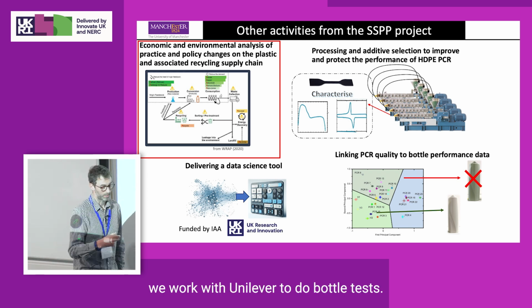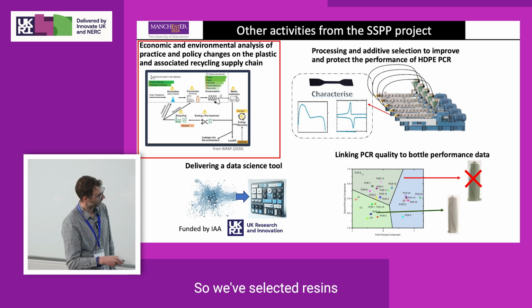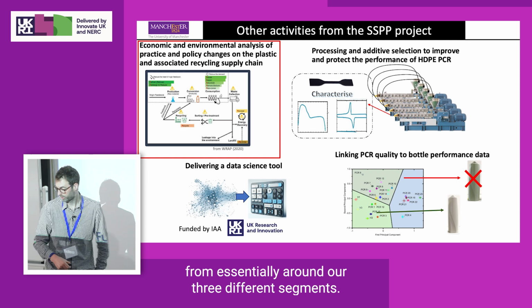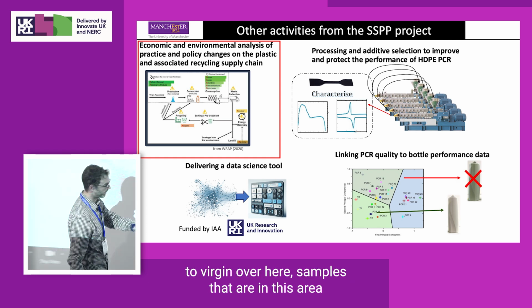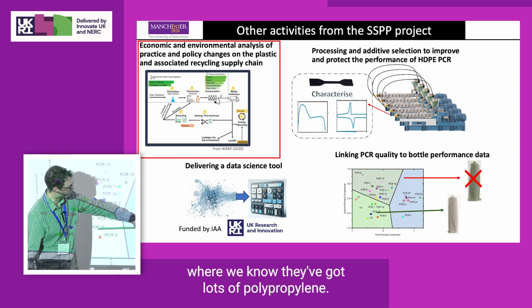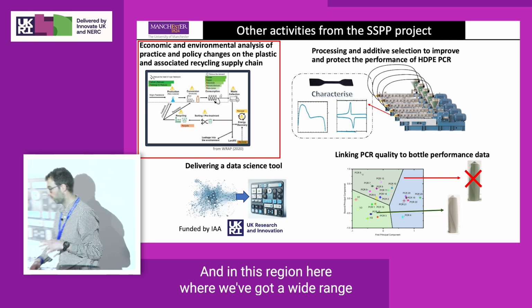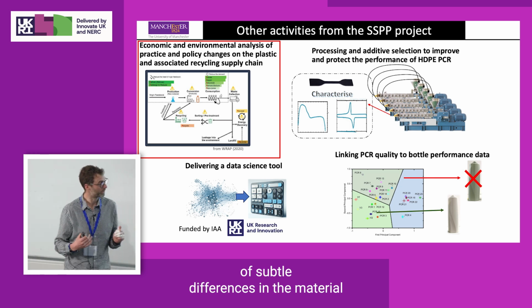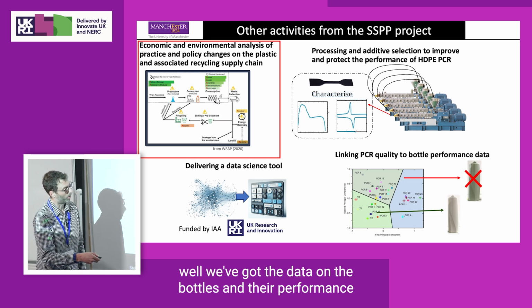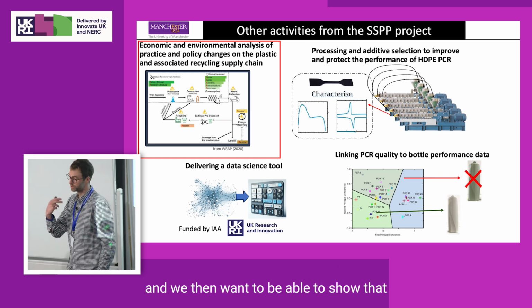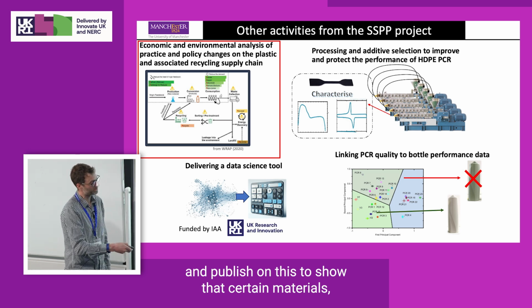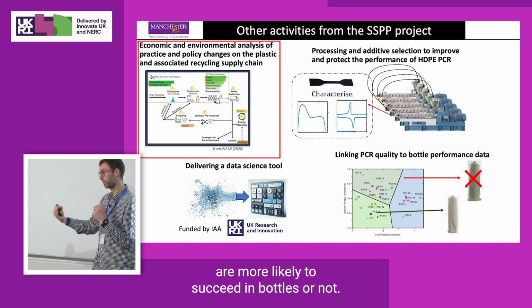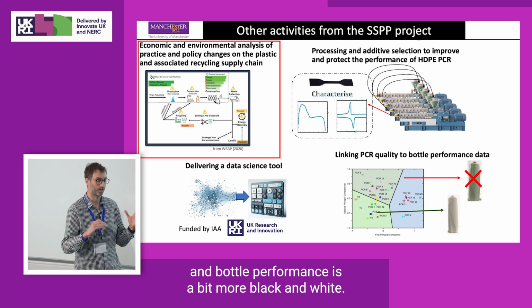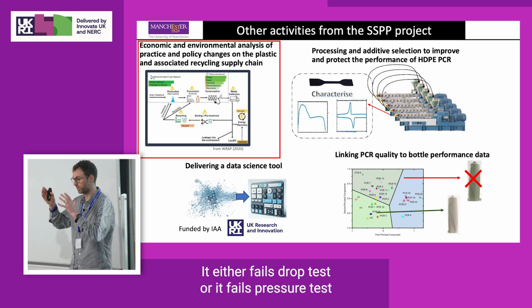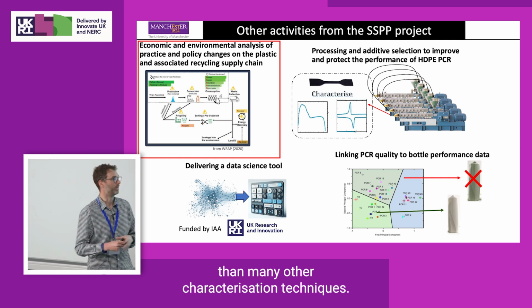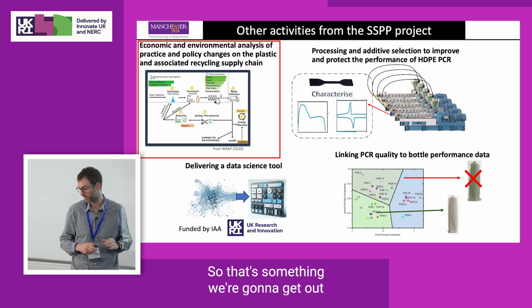And finally, and really critically, we worked with Unilever to do bottle tests. So we've selected resins from around our 3 different segments: resins that are similar to virgin over here, samples in this area where we know they've got lots of polypropylene, and in this region here where we've got a wide range of subtle differences in the material. We've got the data on the bottles and their performance, and we want to publish to show that certain materials, depending where they sit on here, are more likely to succeed in bottles or not. The challenge is that bottle performance is a bit more black and white. It either fails the drop test or it fails the pressure test, more than many other characterization techniques. So that's something we're going to get out in the next couple of months.